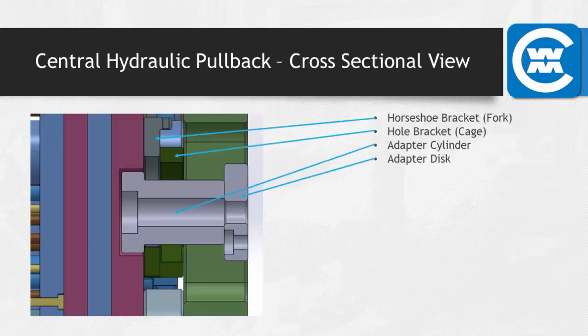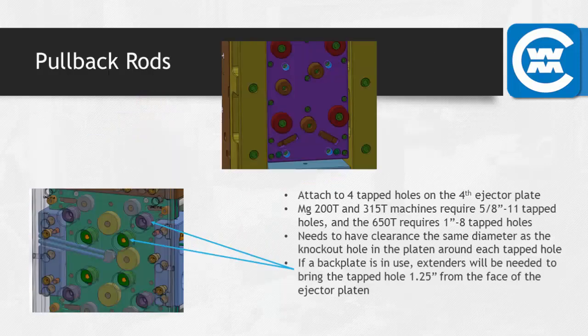And here's a cross-sectional view. The adapter disc that you see right here is actually attached to the machine and moves the system back and forth. When the die is set up, the horseshoe bracket, which is this piece right here, actually gets inserted from the top and then locks into this in between the cage and the ejection system in the die, and that's what holds everything together, allowing it to move back and forth. So then when you're ready to remove the die, you just remove this fork from the top again and you're ready to tear down the setup. Pullback rods are a little bit different, but in general accomplish the same thing. Rather than attaching the machine to the die with that horseshoe bracket that we mentioned in the previous slide, the pullback rods directly thread into the ejector plates and the machine, joining them together.